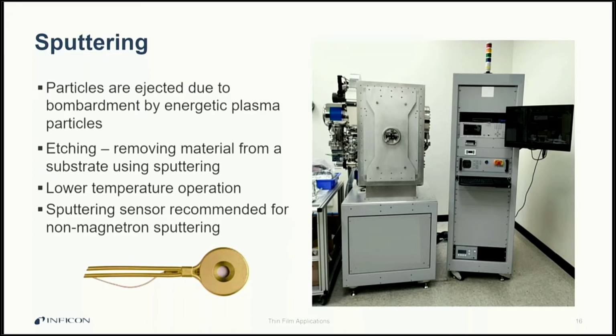In sputtering applications, you can either deposit material onto a substrate or etch material away from a substrate. And when you're etching material away from a substrate, the substrate is actually the target.